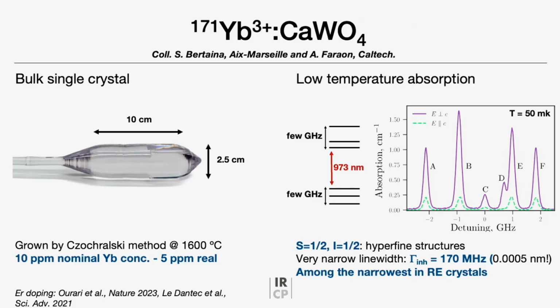If at low temperature, so here we are at 50 milli-K, you record the absorption of the crystal, you see all these lines appearing on the main peak here. You see that the absorption is actually not so low. In a 1 centimeter long crystal, you would already absorb something like 80% of the light, even though the doping concentration is really low. And why is this?